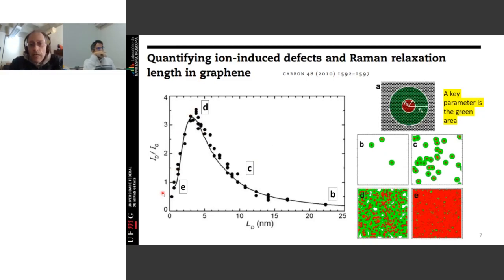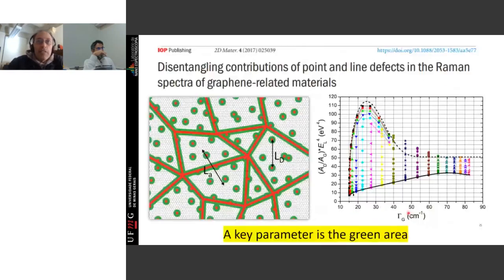Everything that I show you here is done at the macroscopic level. We illuminate the amount of material with all these things, and then you can do something that is more interesting. You can have defects that are points, or you can have defects that are grain boundaries. And the grain boundaries will again have the grain boundary itself and the region, which is green, where the electronic structure feels the defect region that's there, okay? And since we have two pieces of information now, one is the distance between point defects and the other is the size or the distance between crystallites, using two spectroscopic pieces of information, you can disentangle the amount of point defects and line defects that you have.